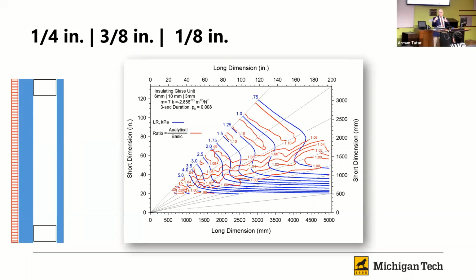to offset the pillowing effect. And so if you've ever been to a downtown area where it's really cold, usually it's very noticeable. You can see some weird undulations or reflections on the glass. And what that is, is because that airspace either expanded or contracted. And the further you are away from the building, the more noticeable that deformation is. And so to combat that, if we put the thicker one on the outside, then that will stay relatively flat. And the interior one, which we don't care too much about, will kind of allow that airspace to expand and contract, and you don't see that deformation.